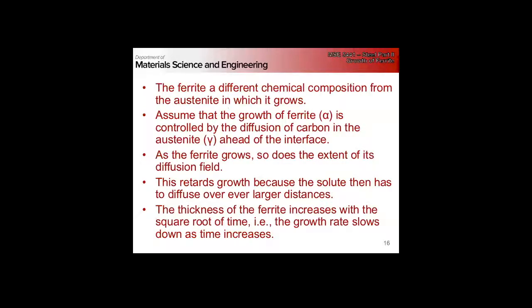Okay, so because it's diffusional growth, our main limitation is going to be our diffusion of carbon in front of the interface. And so we're rejecting carbon from the ferrite.